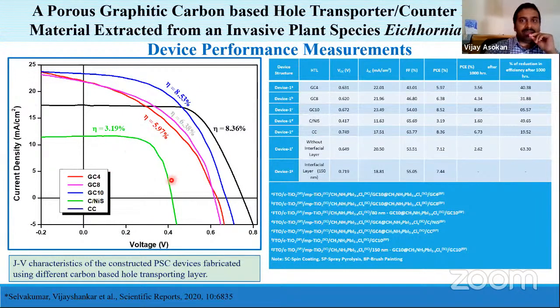We try to calculate the efficiencies, and we have constructed a number of devices by using different combinations. For example, you see here the perovskite layer and 1000-degree annealed carbon mixed with perovskite, because this is going to be the interface, and with different ratios we have used, and different morphological carbons we have used. We have constructed a number of devices, shown here with different combinations of HTL, and we have calculated the efficiencies.